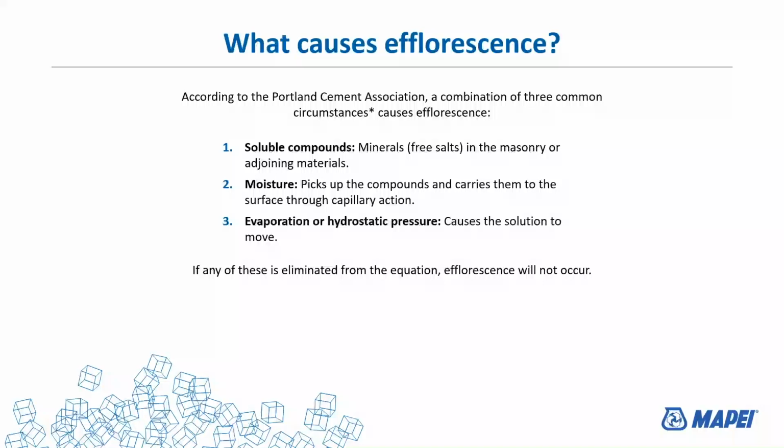There has to be moisture available to wick it through capillary action to the top, and bring it up through evaporation from wherever the sources are coming from. Moisture is the driving issue. That's what brings it to the top. And once you get the evaporation, that causes it to move, bringing the moisture and the minerals up at the same time.